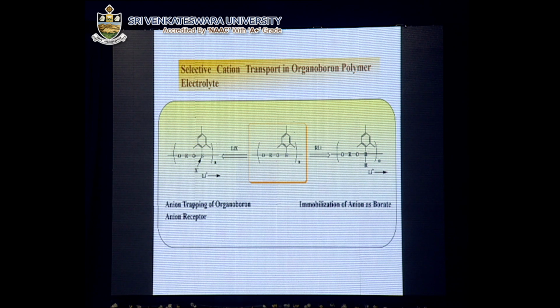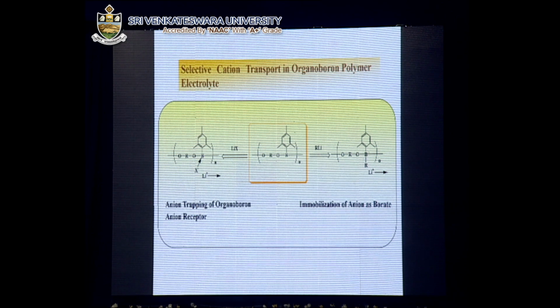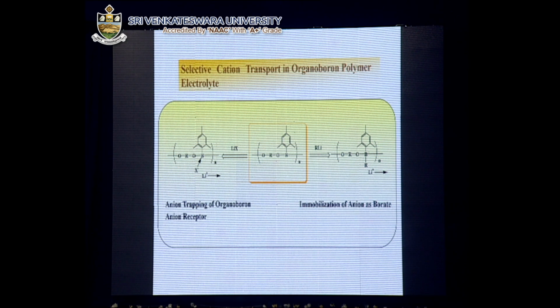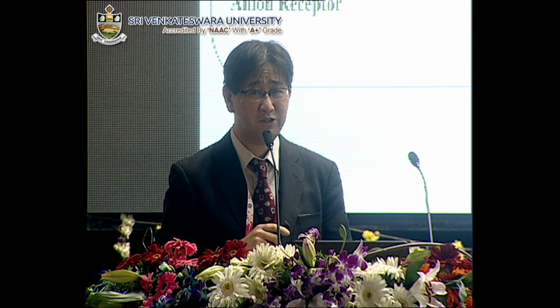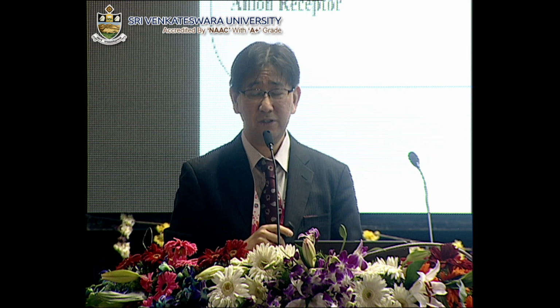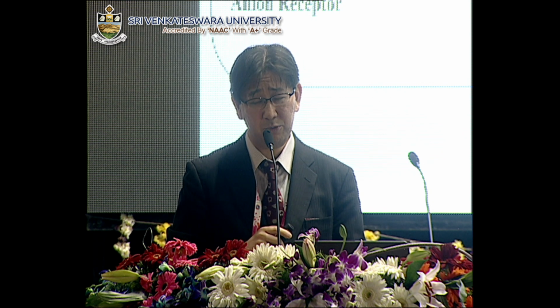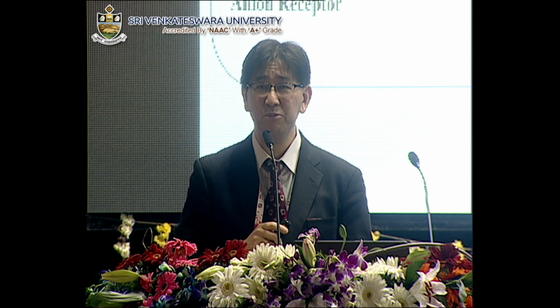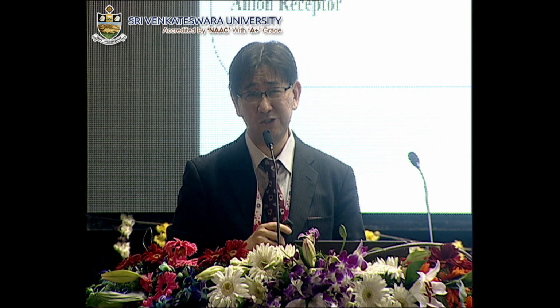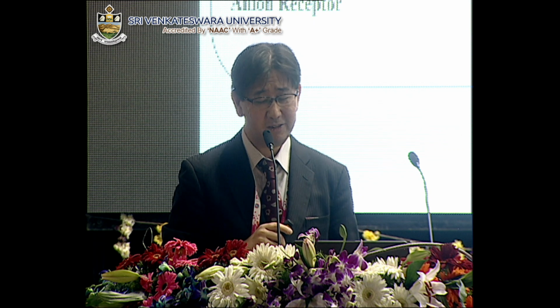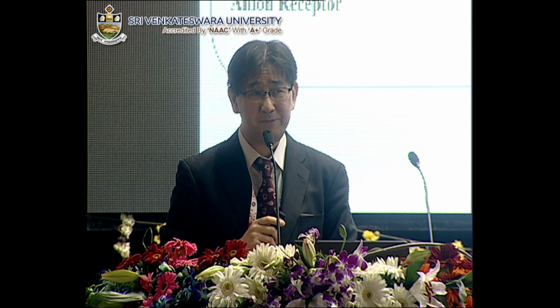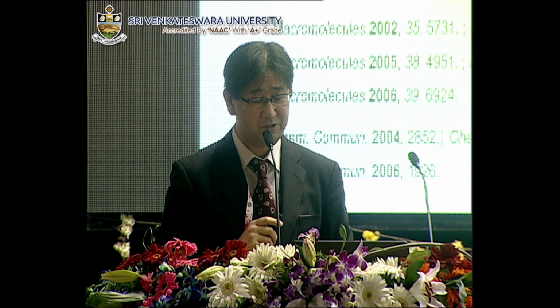And after introduction of tricoordinate boron in the main chain of the polymer electrolyte, in the presence of lithium salt, boron trapped anions efficiently and thereby enhanced the selectivity for lithium cation transport. And on the other hand, after the polymer reaction of the organoboron polymer with an organolithium reagent, the anionic charge was immobilized on the polymer chain, and this also led to much enhanced lithium transport.